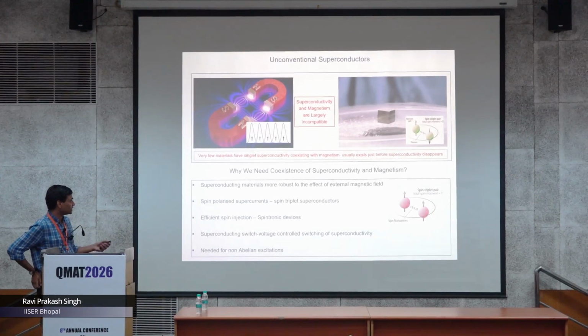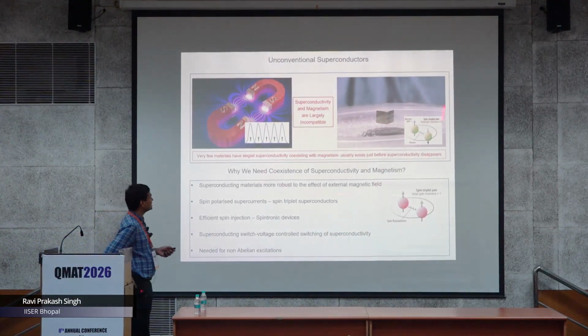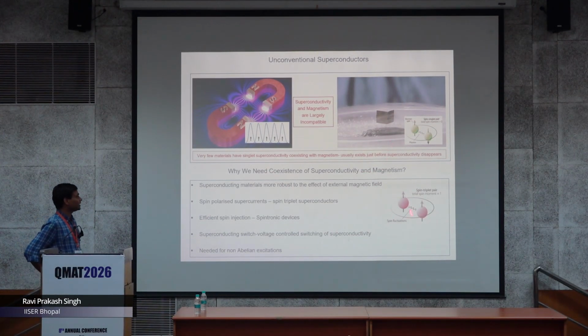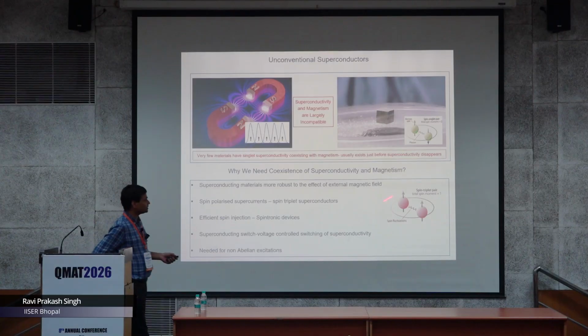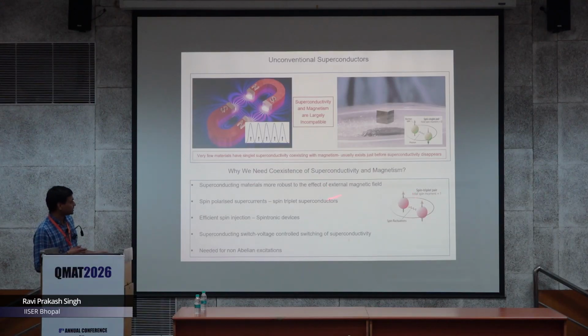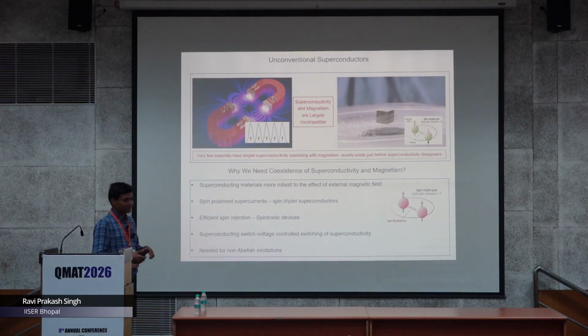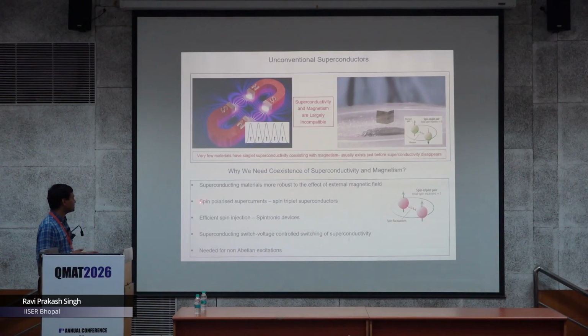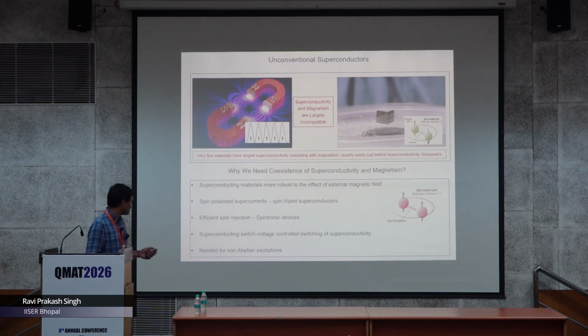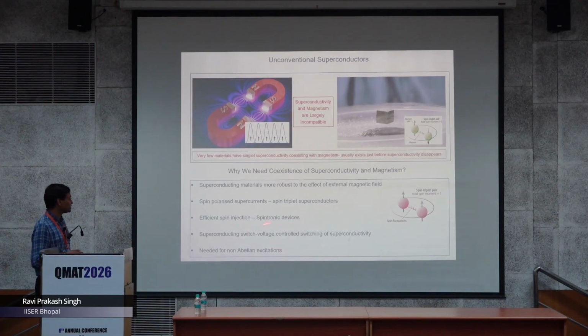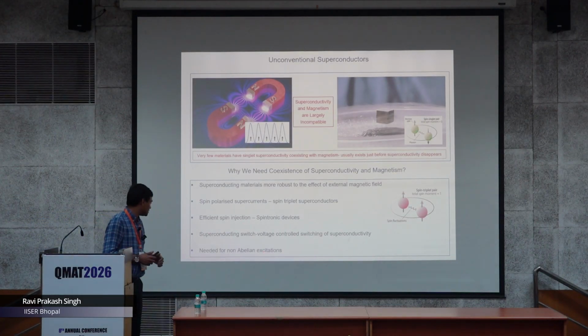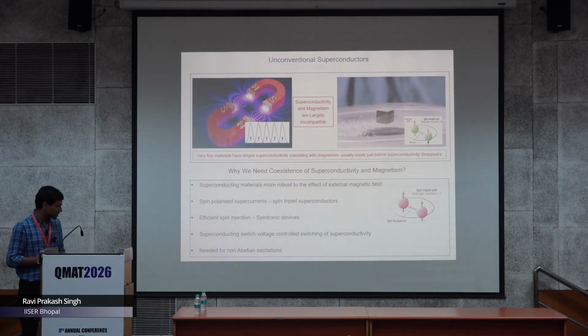Before moving forward, I will give you more detail on why you need this kind of superconductor. If I am talking about a superconductor where both spins are up, it is called a spin triplet. If this kind of Cooper pair is there, it can withstand a very large magnetic field, so you can get better magnets and other things. You can get spin polarized supercurrents. Then you can also use it for spintronics devices, because you can get efficient spin injection. And you can also get voltage control switching of the superconductivity.